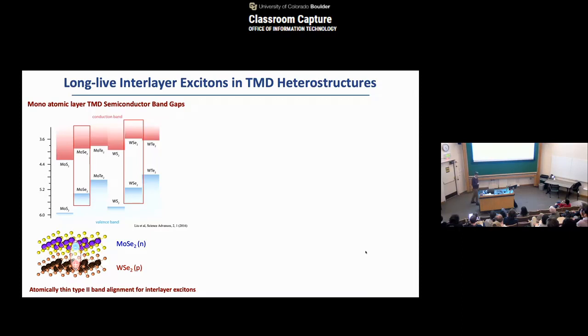So that's good. Also, these are really tightly bound to each other because the layers are very thin, and there's a van der Waals gap between them, which means that you have to almost get outside into the vacuum and come back. So although this is a thin barrier, it is tall enough such that wave function overlap is minimized, right? So immediately you get huge binding energies and reasonably long exciton lifetimes here, right?